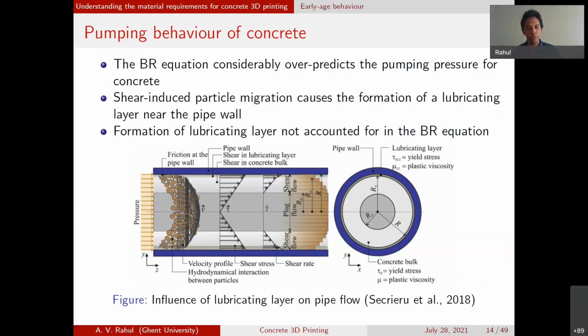So when you try to pump a fluid like concrete, some liquid phase in the concrete can separate out under the shearing action and form a thin layer, as you see here. This thin layer occurs on the pipe edge, and it also becomes sheared. Within this lubricating layer, the bulk concrete is sheared, and once the stress level goes below its yield stress, you see the plug occurring at the center.